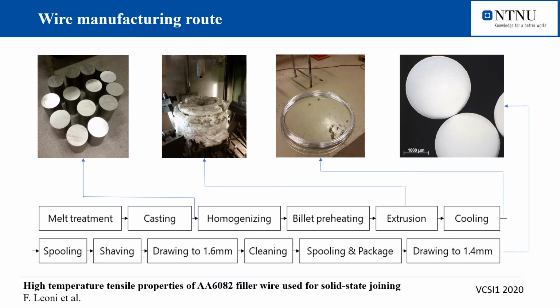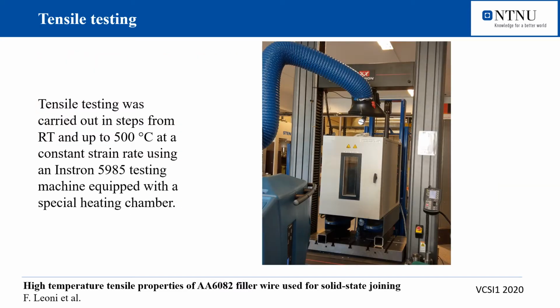Following extrusion, the blank wire was first shaved and then cold drawn in steps down to the final diameter of 1.4 mm. In the cold drawn condition, the wire displays a Vickers hardness of about 130, and besides some minor surface imperfections, the wire surface appeared smooth and contained no cracks. Tensile testing was carried out in steps from room temperature to 500 degrees at a constant strain rate of 0.0011 per second, using an Instron 5985 testing machine equipped with a special heating chamber and special grippers that made testing of the thin wire possible.